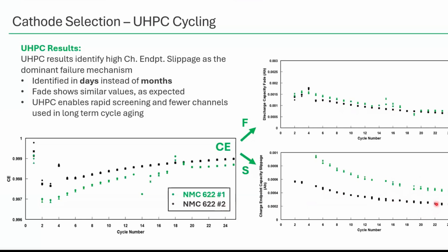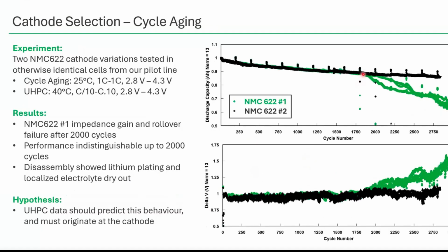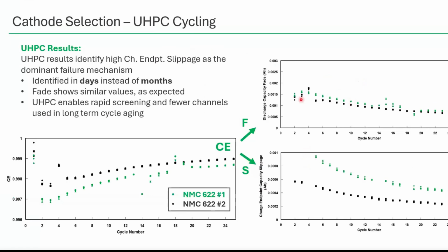These are really big differences in UHPC that would otherwise be in the noise of other types of cyclers. So it's really key to know that just in a couple days, this trend doesn't change. In just a couple cycles, we would have been able to conclude this cell has a lot more charge endpoint capacity slippage, and it's likely going to fail sooner. Again, this doesn't show up for months and months into normal cycling when we can see it in days with UHPC.